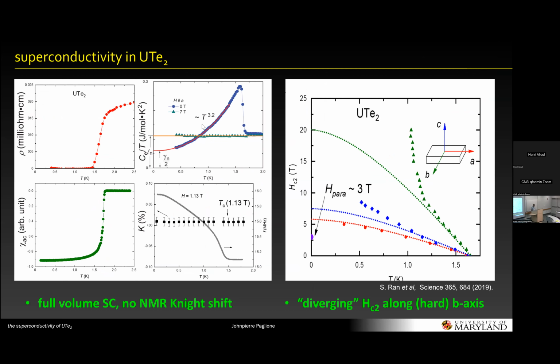Okay, the basic properties are TC between 1.5 and 2 K. The amazing thing is that the upper critical field is enormous, at least in the B-axis direction. The first measurement was off scale, and for a 1.5 Kelvin superconductor, that's quite amazing. And I know my colleague Nick often shows this phase diagram of HC2 for different superconductors, where the Chevrel phases, of course, have a huge one. But you know, UTe2 is like a delta function at 0. TC is very low, and the upper critical field is enormous.